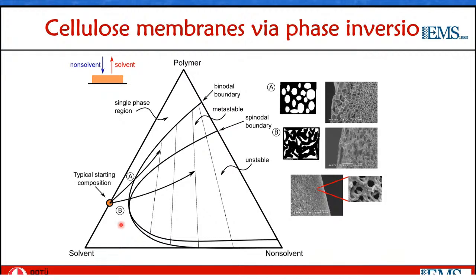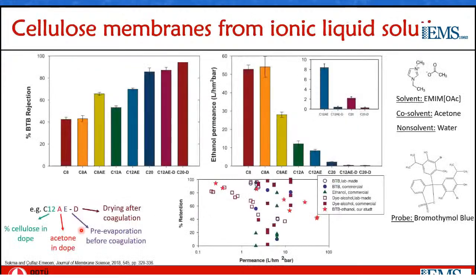And then obviously, if you're going to make a membrane by phase inversion, we need to be able to dissolve our membrane polymer in some solvent. And as I mentioned, for cellulose, this has been more difficult, but now with the developments in ionic liquids, which are molten salts that are liquid at below 100 degrees, with the developments in these ionic liquids that can directly dissolve cellulose, this has become more easily possible.